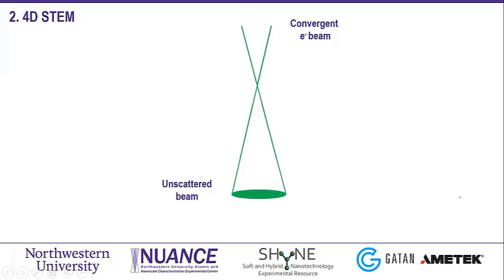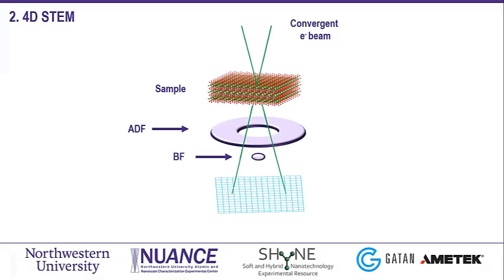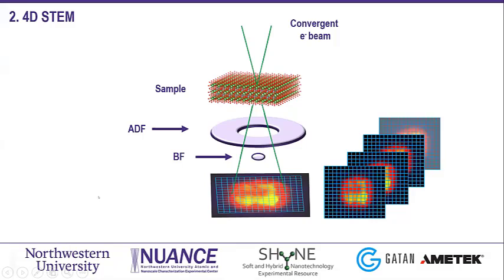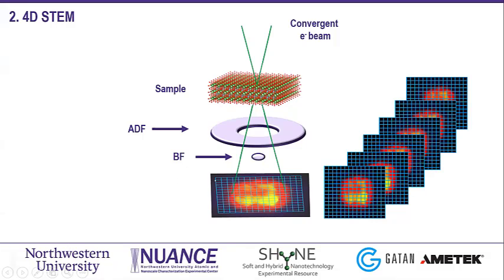For those that are not familiar with STEM, the lenses in your microscope converge the beam to a point, and if you are in vacuum, you create this beam on your screen. When you insert the sample there, the sample scatters the electrons, and you can collect the information, the image, using annular dark field, for example, or bright field, right? But you miss a lot of information when you could be collecting your actual CBED, your convergent beam electron diffraction here. And then with the evolution of the detectors, more specifically the direct detectors here, you can actually simultaneously acquire your annular dark field and a diffraction pattern.